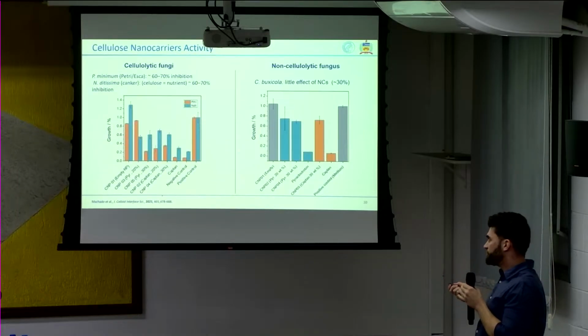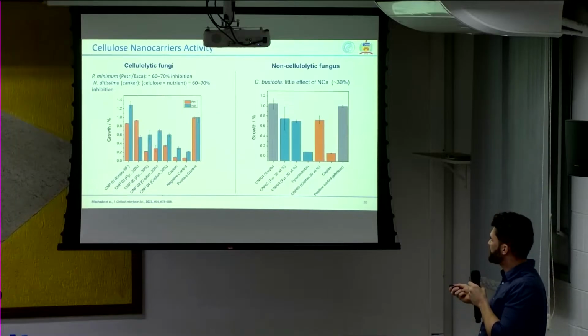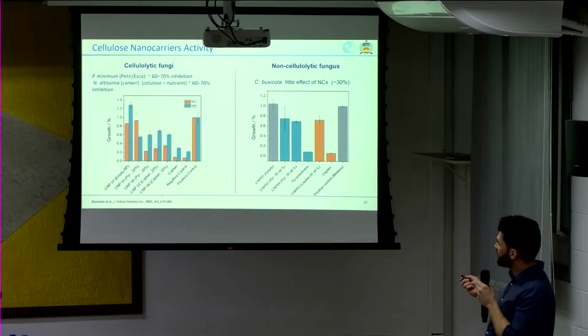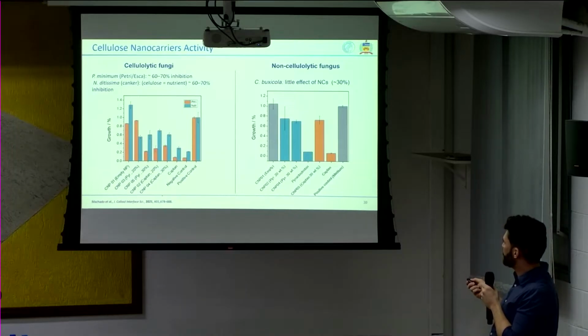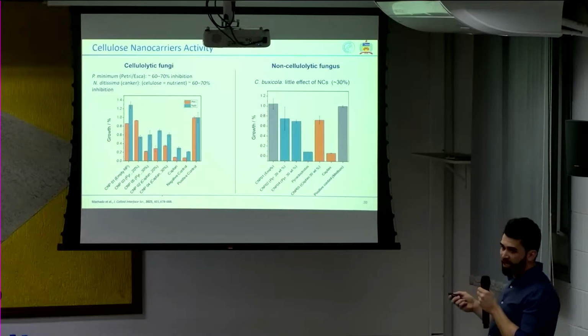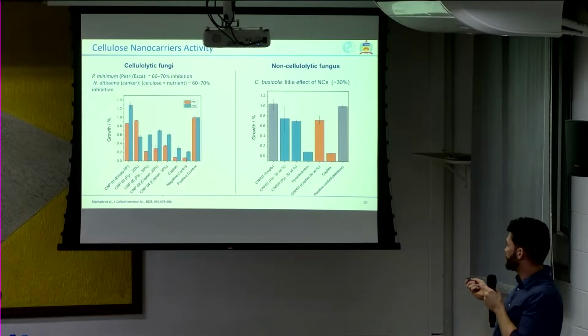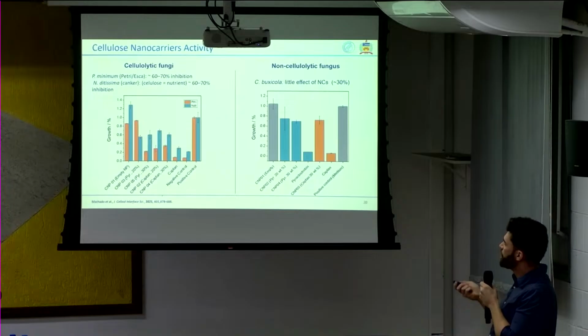And for the cellulose nanocarriers, we did a similar study in vitro only, with the encapsulated fungicide or the nanoformulations showing up to 70% inhibition. And we tested against a non-cellulolytic fungus. So this fungus here cannot degrade cellulose because it doesn't produce cellulase, the enzyme that breaks down cellulose. And the inhibition that we see here from the nanocarriers is just because of the diffusion of the fungicide. So the inhibition here was much lower, so only 30%. That's because of the diffusion. So it means here that if we exclude the diffusion, we still get further inhibition, and that's because of the degradation of the nanoparticles by the fungi.